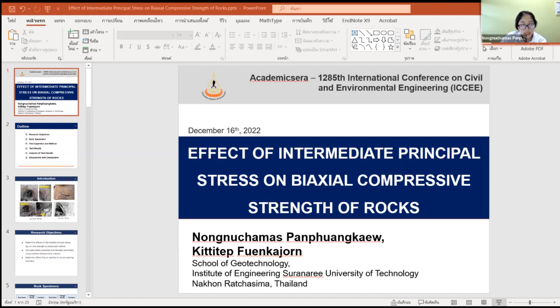From these diagrams, elastic parameters for the 9 rock types show that both elastic modulus and Poisson ratio tend to be independent of the changes of intermediate principal stress and load parameter. And this may be due to the intrinsic variabilities of the rock. About strength criteria, the modified Wiebols and Cook criteria is used to describe the test results as it's capable of incorporating all 3 principal stress.